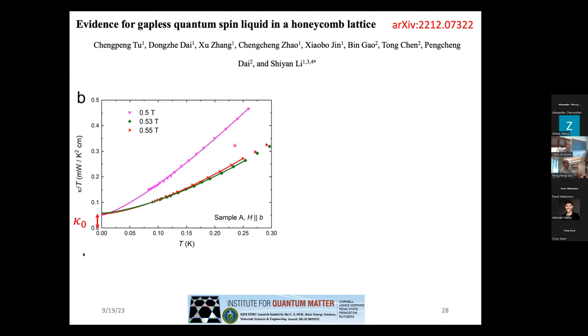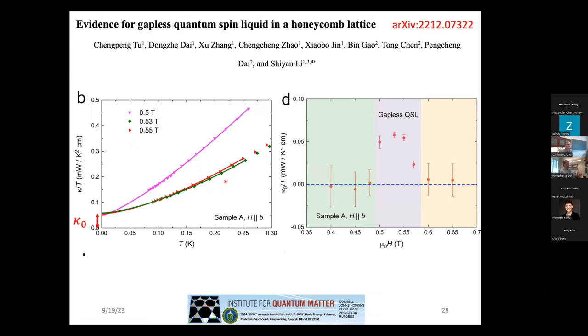And if you zoom in on that critical field regime, you find that they actually do converge towards a finite value. Of course, the measurements were done down to dilution fridge temperatures, not to really zero temperature, and so there is some kind of an extrapolation taking place. But from that, there's a regime of fields where you actually have a finite limit of kappa over T. So that's a really interesting observation.